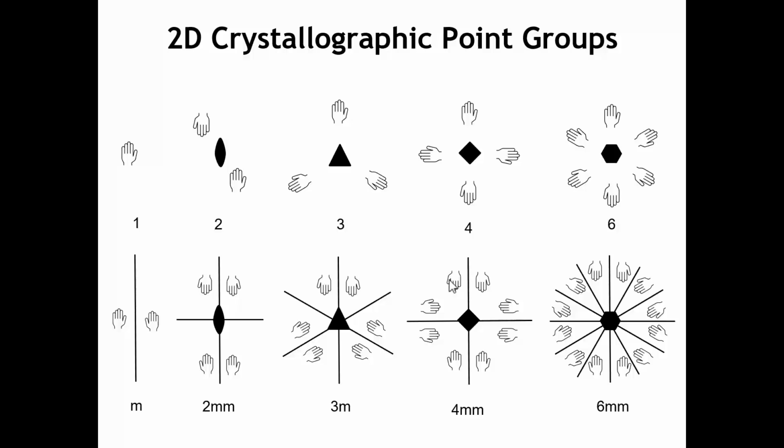We haven't talked about point group symmetry in 2 dimensions, but the 2-dimensional case is considerably simpler than the 3-dimensional case. Because we don't have a 3rd dimension, there are several symmetry elements that we don't have to think about in 2 dimensions. For example, there's no inversion center, because the inversion center would be exactly the same as a 2-fold rotation axis. Because there's no inversion center, then there's no roto-inversion axes, so we don't have any improper rotation axes. There is no screw axes. And of course, we don't have to consider perpendicular symmetry elements, perpendicular mirrors, or perpendicular rotation axes.